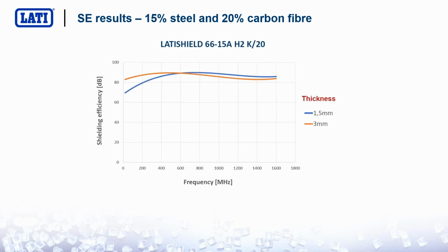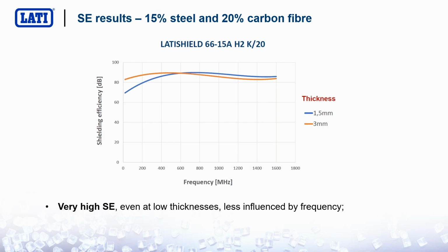What we found is that the result is very interesting because you have a very, very high shielding efficiency, but you have a much lower effect of thickness and frequency. And in our humble opinion, this is a very important result that deserves further investigation, because the efficiency was very high even at low thickness, at 1.5 millimeters, and was less influenced by frequency. Why?